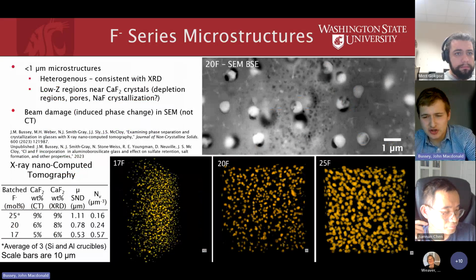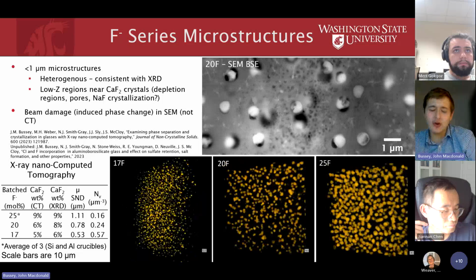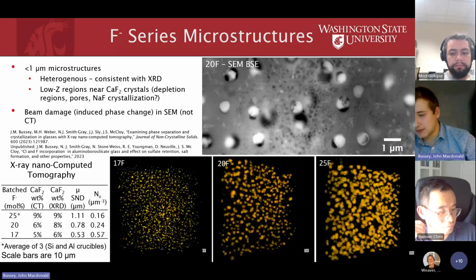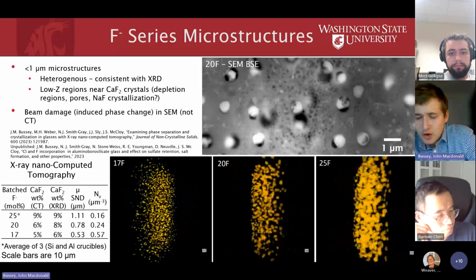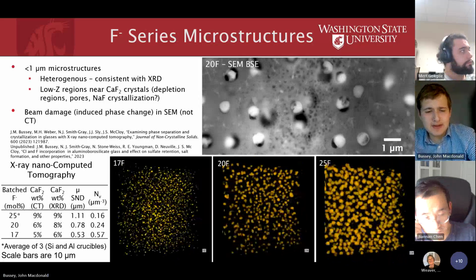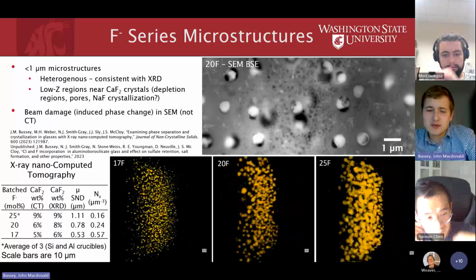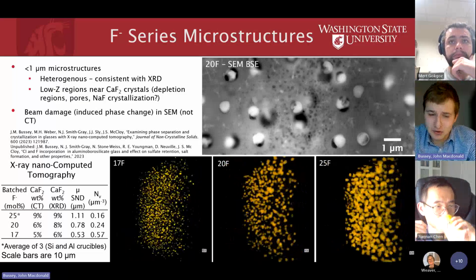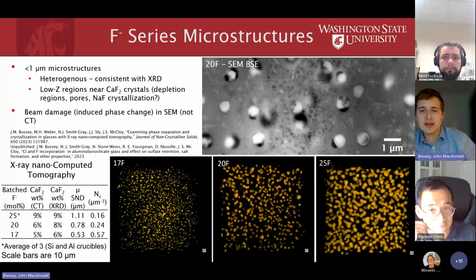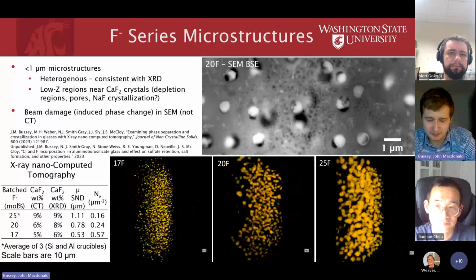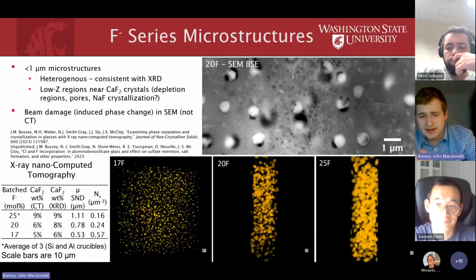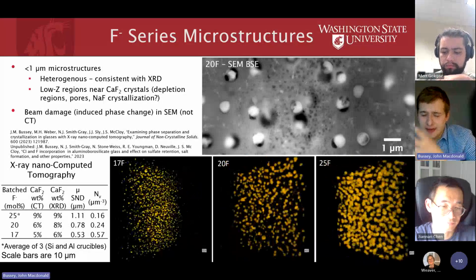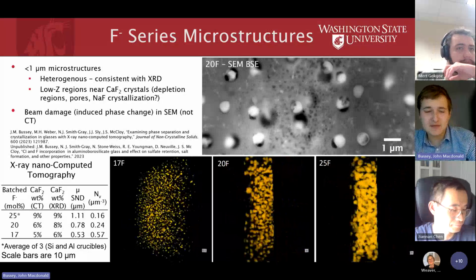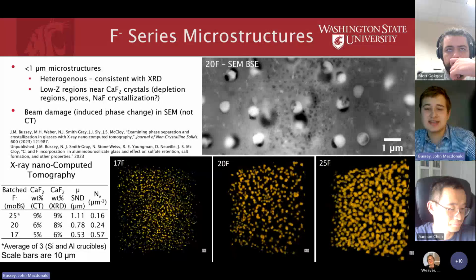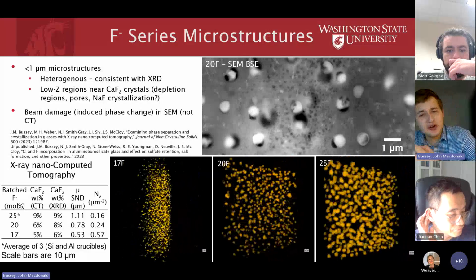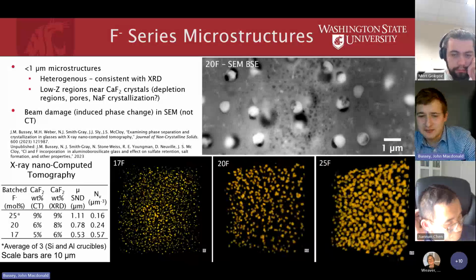Taking a look at the microstructures, unlike the salt phase in the chlorine glasses, where we got two very stratified, different salt layers, in the fluorine glasses what we have instead are these strange spherical-ish micron and submicron sized particles. The calcium fluoride are the biggest, followed by smaller phases that correspond to the other minor crystallites. The key takeaway here is that the excess fluorine, instead of being released as a salt or as a volatile, is retained within the glass. Even though they're crystals, which, depending on the crystal, is not ideal, it's still retained.